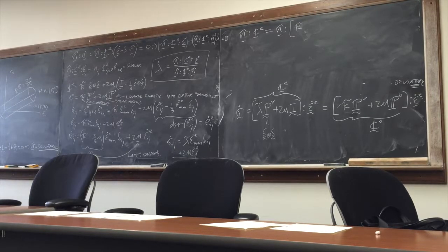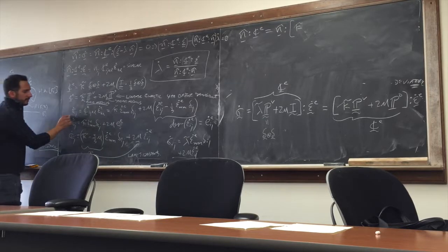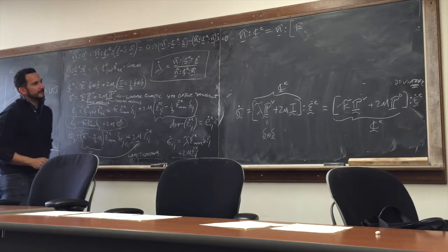And elasticity assumes that those two processes are independent of each other, meaning an increase in shear strain yields no increase in volumetric stress. In plasticity, that's in general not true. You can have processes that are associated with each other, coupled. You can have a shearing deformation that induces an increase in pressure, something that in linear elasticity you can never get. So I just wanted to point that out because I think that's important. Okay? So keep an eye on this.